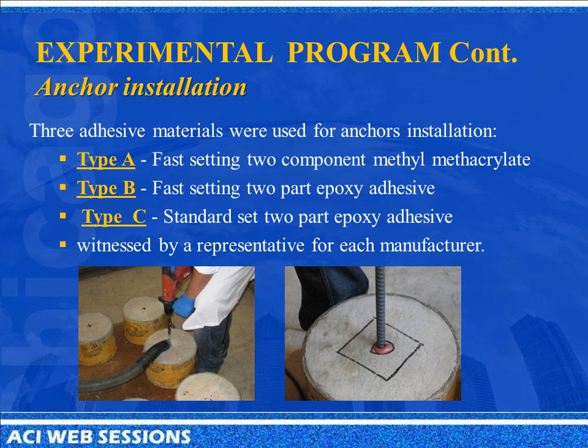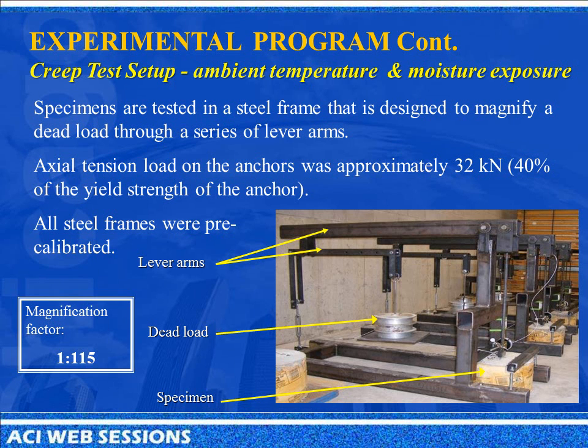During installation of the anchors, we got a representative from each manufacturer to witness the installation, just to avoid any so-called gross errors in installation. For the creep testing setups, we had to adopt two setups for logistics. For the ambient temperature and moisture exposure, we fabricated steel frames that used a series of lever arms to magnify a given dead load to the required tensile load on an anchor, like you see here.